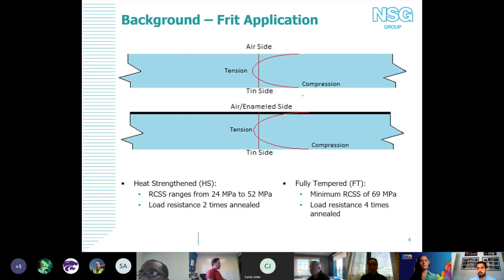In this top picture, you'll see this is a piece of glass that doesn't have any frit or enamel on it, and you have this symmetric residual stress within the glass, where you have tension in the center and you have this layer of compression along the surface, and that's really what's giving it the additional strength that you're looking for. Whenever you add that ceramic frit, you actually have an asymmetric surface stress at the glass surface, at least, because theoretically your maximum residual compressive surface stress should be occurring on the surface of the enamel.